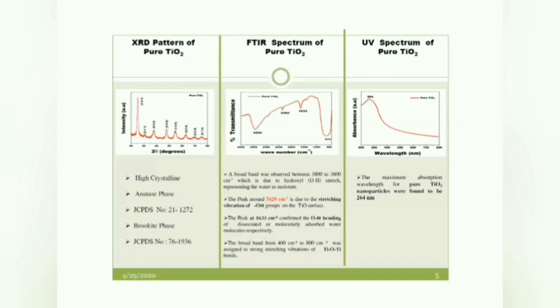Now, from the XRD pattern, you can see there is a sharp peak around 101, which indicates it is highly crystalline and anatase in structure. It matches with the JCPDS number 21-1272, and we are able to get a small amount of brookite phase, because as you increase your temperature, the brookite phase decreases. So that is the reason we get a mixture of these.